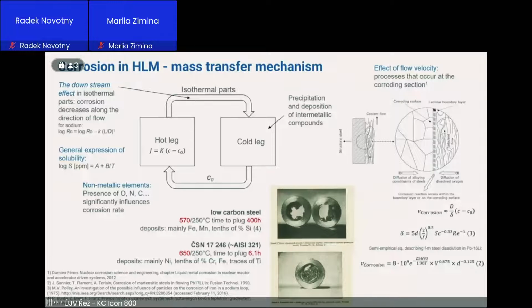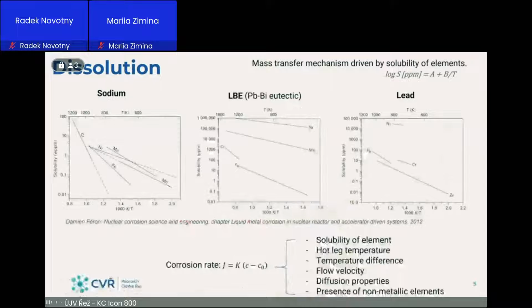So the main factors are temperature and solubility of these elements, and flow rate, of course, because there is a boundary between metal and flowing coolant near the wall, whose thickness controls the diffusion processes and the speed of your dissolution. There is a comparison of different coolants. For example, sodium was used in the past because there is no corrosion of stainless steel because of very low solubility of steel elements in it.